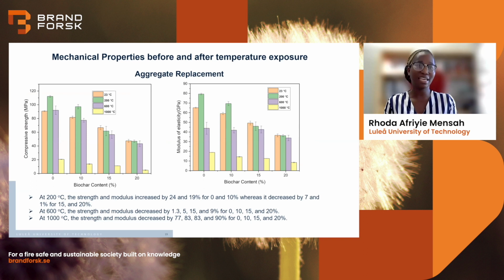We realized that at 200 degrees Celsius, the strength and modulus increased for the 0 and 10%, but for 15 and 20%, there was a decrease in strength. At 600 degrees Celsius, the reduction in strength was similar to that of cement replacement. And at 1,000 degrees Celsius, we also saw a drastic decrease in strength.